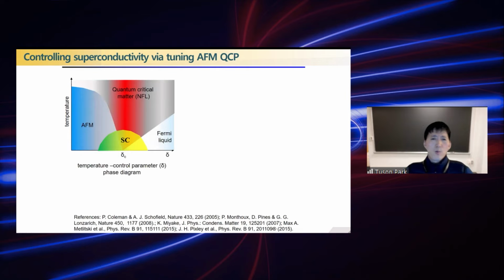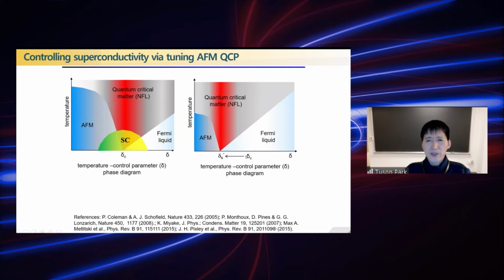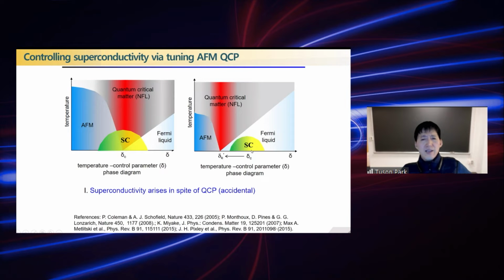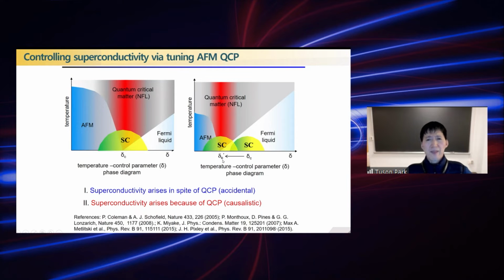Well, to summarize this approach, we can usually see superconductivity arise in the vicinity of the AFM QCP. What the theory predicts is that if you move the critical point to another point, there may be a case where the superconductivity does not move at all, meaning that the superconductivity does not arise because of a QCP; it's just purely accidental. However, if they move together, then it's a very strong argument that superconductivity arises because of the quantum critical point.